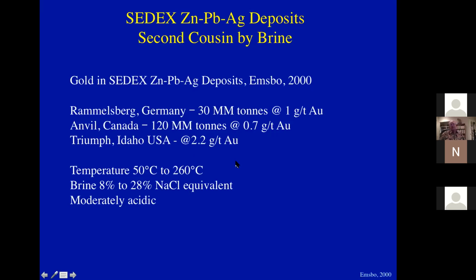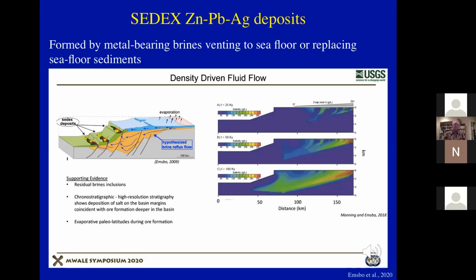Now, these SEDEX, zinc, lead, silver deposits were deposited at a temperature of between 50 and 260 degrees centigrade. The brine salinities are 8 to 28% NaCl equivalent. And Paul concluded that the brines were as well moderately acidic. And Paul has advanced a theory that the brine was generated on a carbonate platform by basically sabkha evaporation up here on the platform, generating a brine that, because of its density, migrated through the sedimentary section and then broke through out to the sedimentary basin, either up faults or through mud volcano type breccia pipe vents into the seafloor.